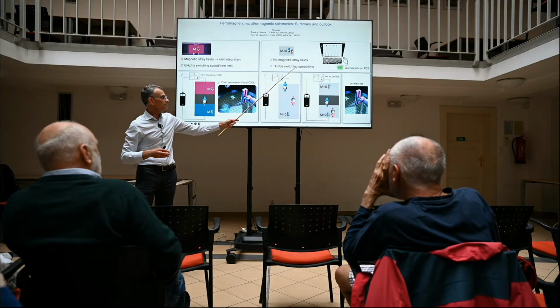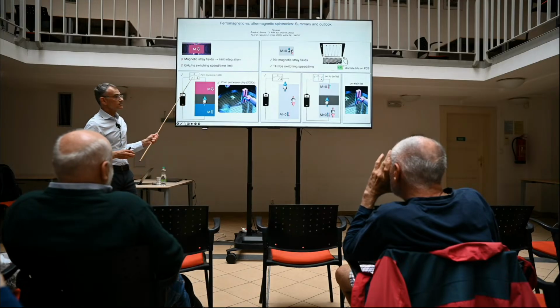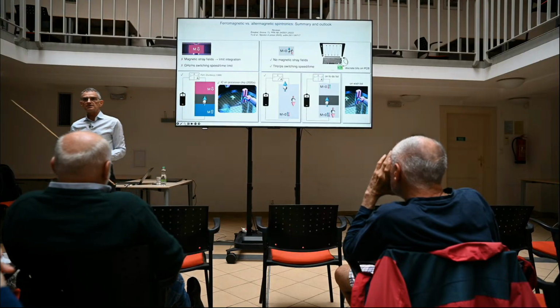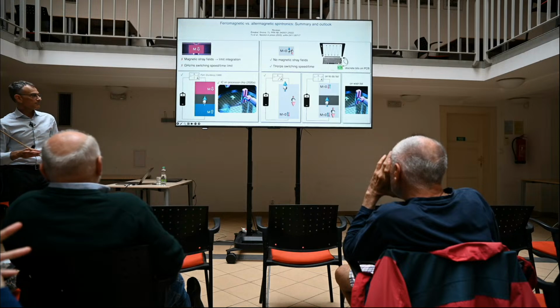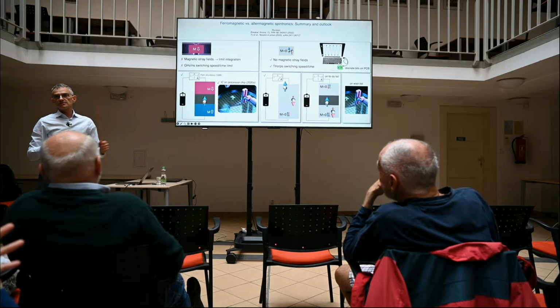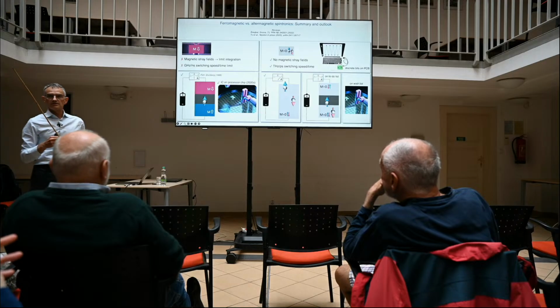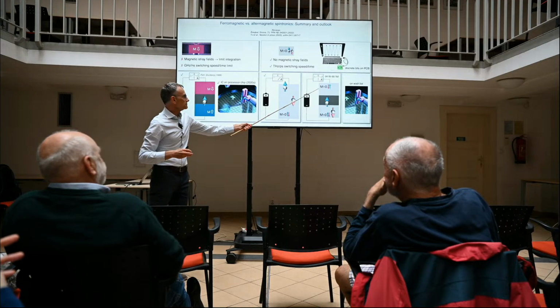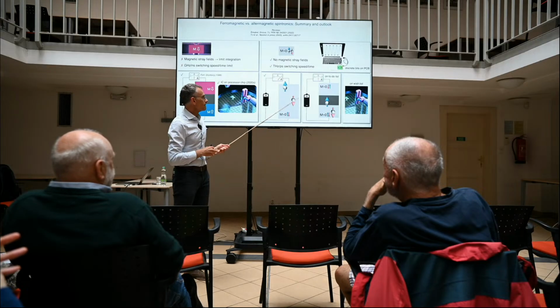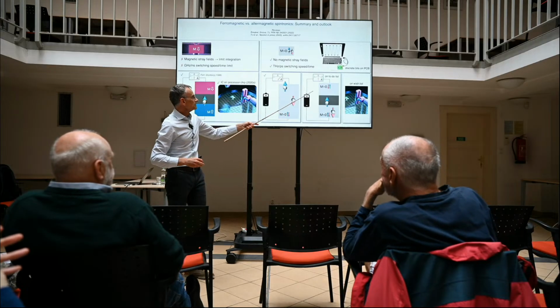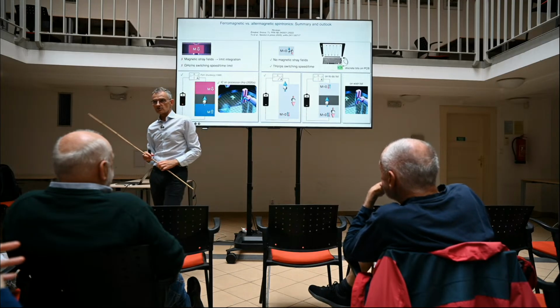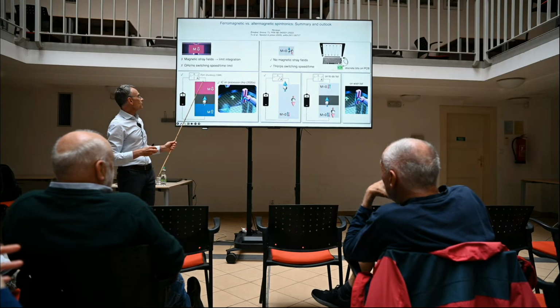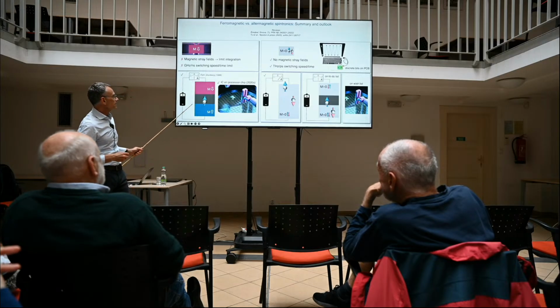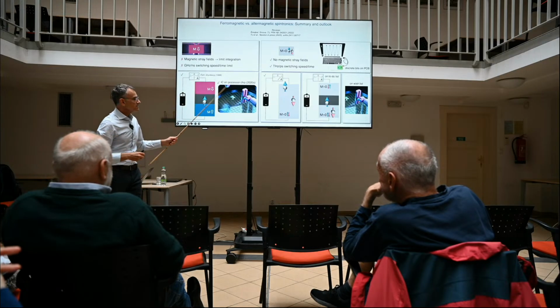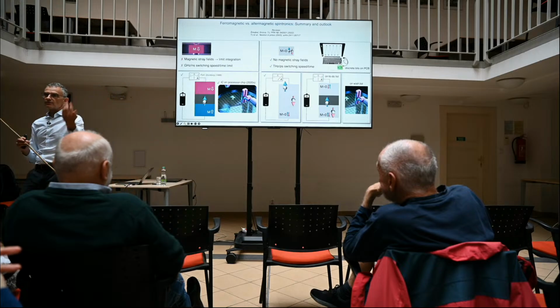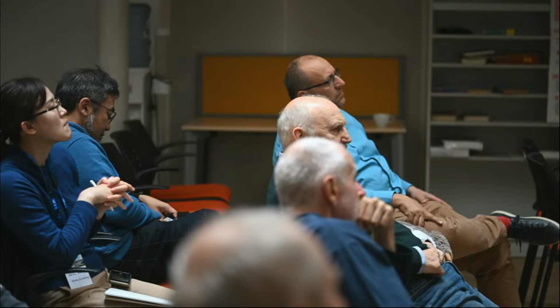It has to be demonstrated, and the key thing is the size of this magnetoresistance effect. If it's only a few percent, it's not going to make it to commercial applications. Here in ferromagnets, we have 200% effects at room temperature, and this is what is needed. That still is yet to be demonstrated in altermagnets. If we have this, we're definitely not immediately commercial, because there are so many more things that have to be shown on the engineering side, that you can take this device and integrate it on the semiconductor wafer or on the semiconductor-based integrated circuits.